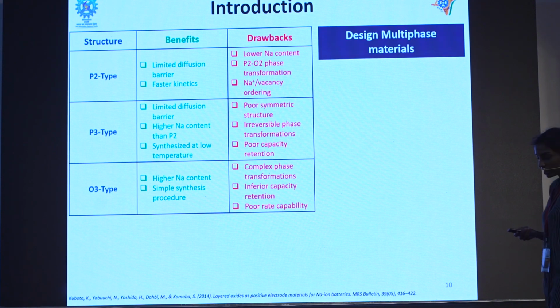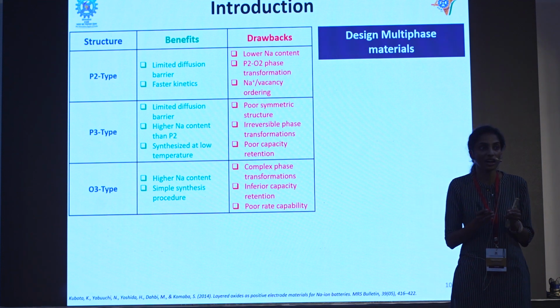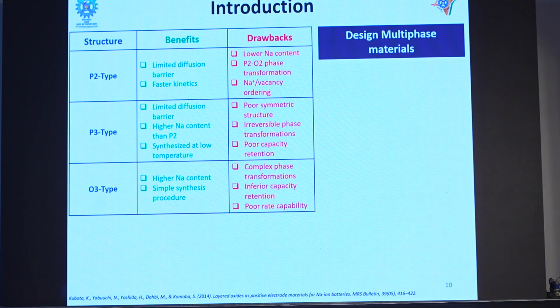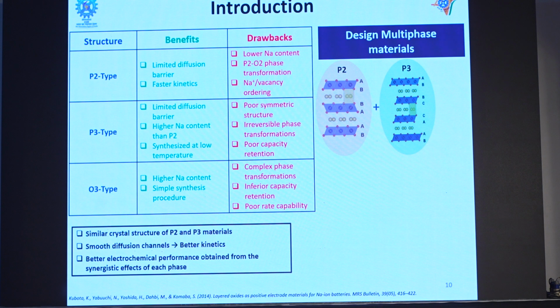So the idea is that if you have a single material, you also have limitations. But if you can combine them at a molecular level, then we can end up with multi-phase materials. These multi-phase materials have a synergistic effect from both the materials, and maybe it will act in such a way that your issues are overcome. So we designed P2, P3 composite materials expecting a high capacity and good upscalability, and we can incorporate a higher sodium content than P2, so we will end up with a higher capacity material.